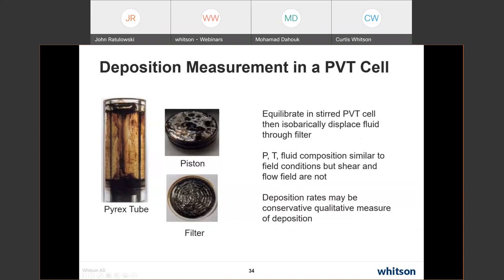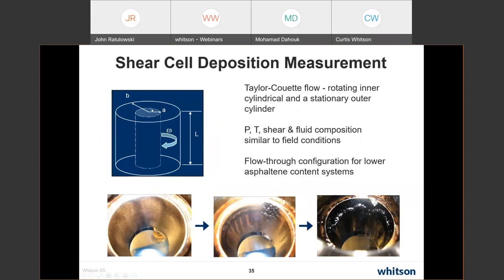All right, this is a shear cell deposition measurement. So what we have is just a Couette, a Taylor-Couette flow. And here we can actually control the wall shear. So what we were trying to do is look at the impact of the wall shear on deposit amount. Because asphaltenes, only a small amount of them actually deposit, we had to flow through this cell for most systems in order to get a substantial deposit building up on the wall.